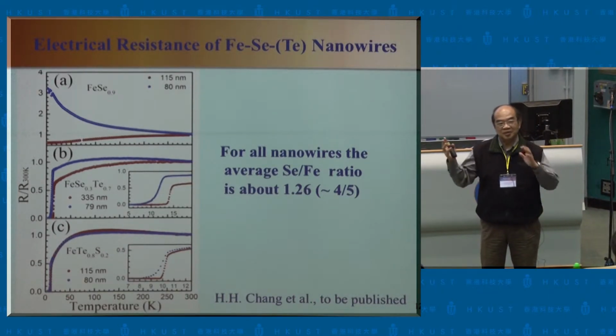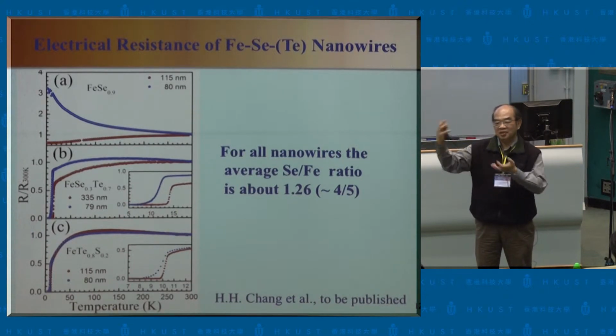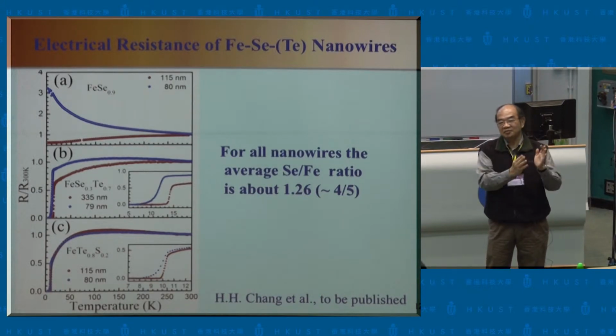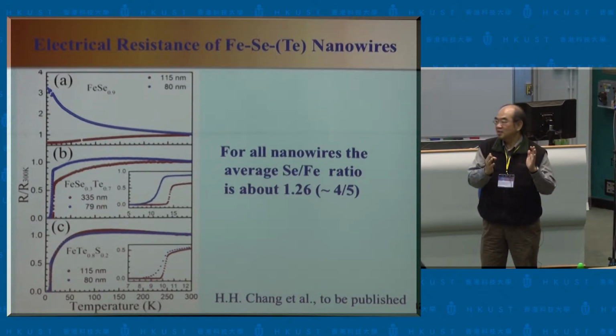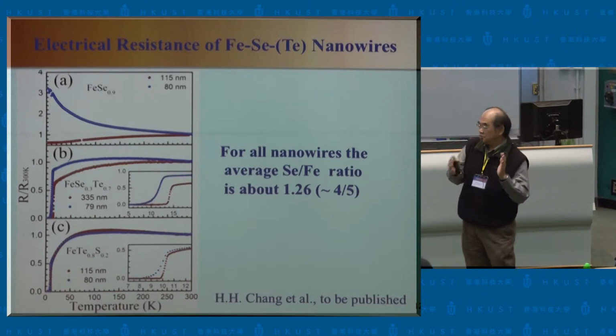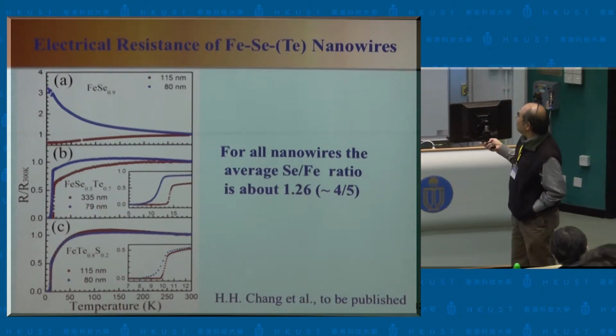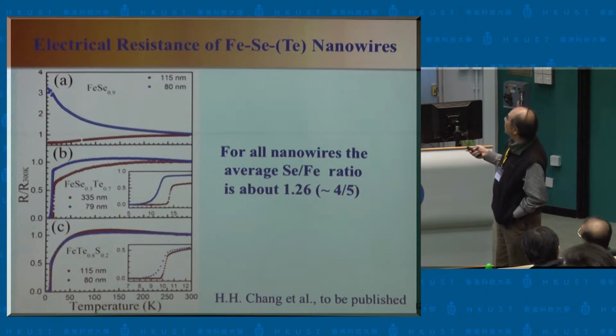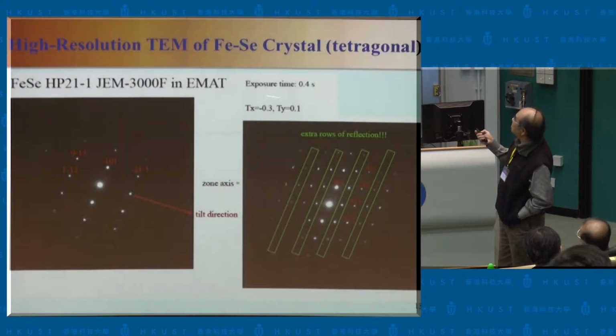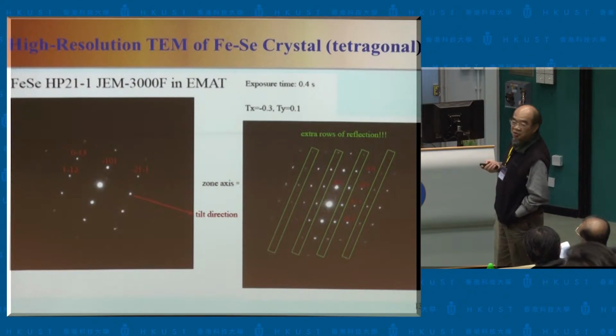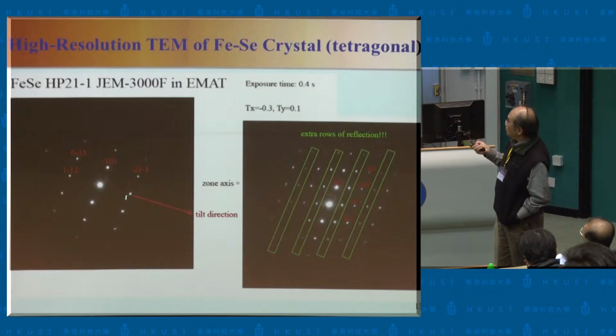Remember, this is a double layer. You have the 2,4,5 compound, which gives you 40 Kelvin. So that means this iron deficiency could really be the important thing in this whole series problem. And in fact, later on, we decided to examine more carefully some of the crystals we grew using a high pressure technique, which are very high quality and give a very good electrical or magnetic transition.